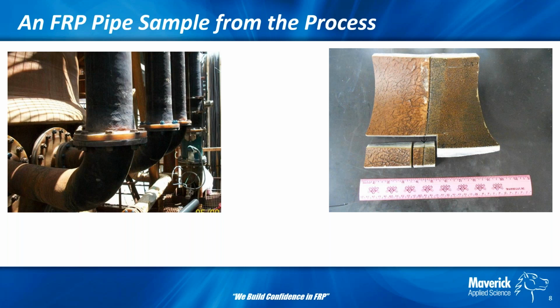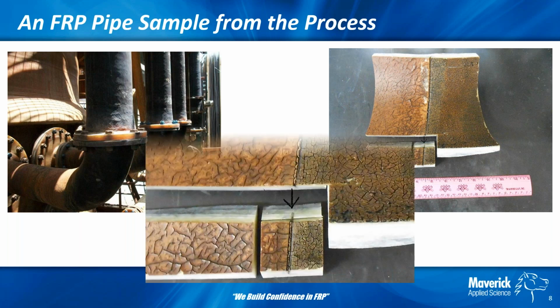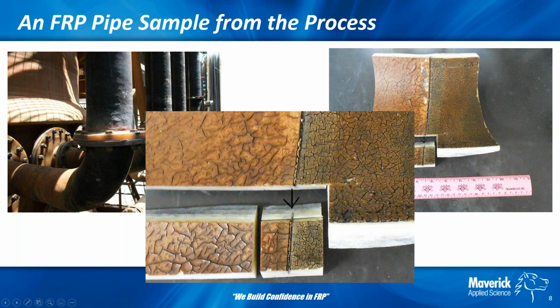So we're going to look down a little bit further. So here's our sample again. Here's a close-up, so you can kind of see that cracking in the corrosion barrier. You can see the cross-section of the structure down underneath here. Looks pretty clear for the most part. Don't see a whole lot of contamination. Compared to other acid surfaces, we haven't found that we get a lot of contamination and permeation into the structure of the laminates.